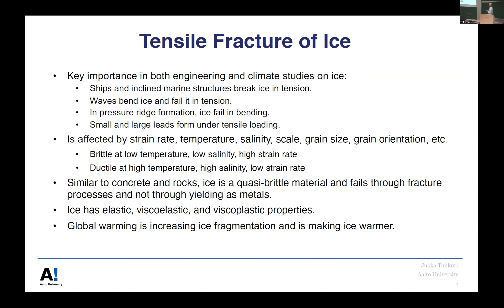An important feature of tensile fracture of ice is that ice is similar to rocks and concrete — what we call quasi-brittle materials — and it is fundamentally different from metals. In metals, yielding occurs at crack tips. In quasi-brittle materials, there's no yielding, but fracture processes and cracks occur. Ice also has elastic, viscoelastic, and viscoplastic properties. Global warming is making ice warmer and generating larger waves, leading to more fragmentation.